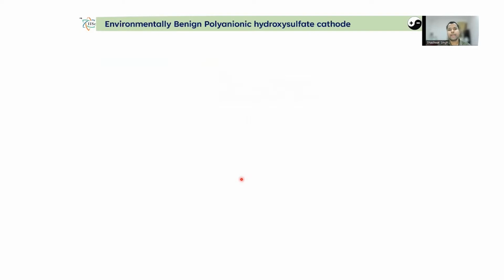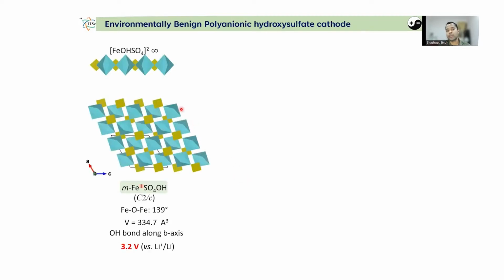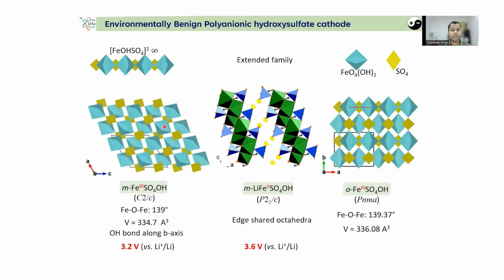Now going ahead, in order to remove fluorine from the LiFeSO4F based system, one can get an FeSO4OH based system. Although the redox potential will come down, the material will become much more moisture resistant, and it is also thought to be non-toxic. Apart from that, these compounds can be synthesized at a very low temperature that makes them very economical, and their precursors are also very sustainable. The first compound from this group was a monoclinic FeSO4OH that was reported in 2009 by the Tarascon group, and it acted as a 3.2 volt lithium-ion battery cathode.